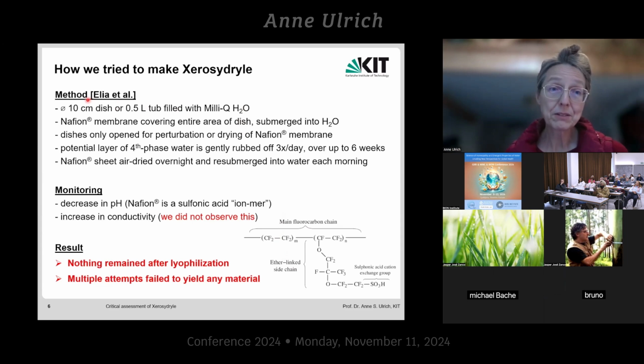We followed the method of Elia and worked very carefully in closed container, even in a clean bench. But, well, we did find a decrease in pH over weeks. But that's not surprising because the material we used as a starting material is Nafion. It's a fluoropolymer that carries very acidic groups. So naturally, when you immerse them in water, they will give off protons and acidify the medium.